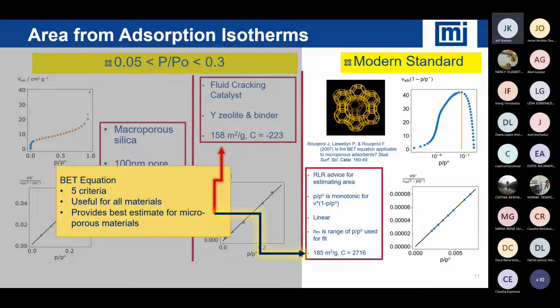The same rules apply, that it has to be linear. And now there's an additional rule that when you calculate surface area, it cannot be an extrapolation. So when I calculate surface area, the data I use for calculation must envelope where we actually predict the surface area will be from BET. So putting all of these rules together now, we can automatically calculate surface area, which is quite nice.